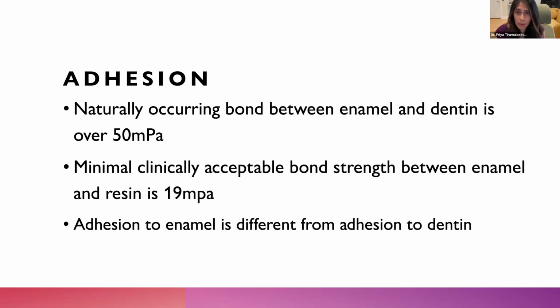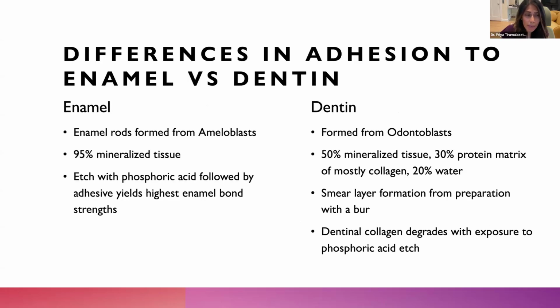So the naturally occurring bond between enamel and dentin is over 50 megapascals, which I was blown away by that number. The minimal clinically acceptable bond strength between enamel and resin is 19 megapascals. So we know that adhesion to enamel is very different from adhesion to dentin. And the reason being, enamel is 95% mineralized tissue. It's hard, and the rods are formed from ameloblasts. And we know that etching with phosphoric acid followed by adhesive yields the highest enamel bond strengths.